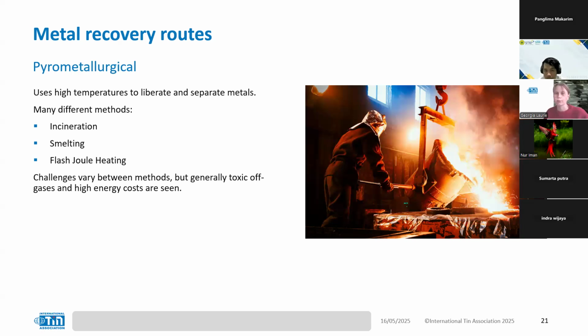This is usually a pre-treatment step to reduce e-waste volume and produce metal-rich residue. The residue can be further refined via smelting or leaching. After incineration, tin is often left behind mostly as an oxide or metal particles mixed with other ash constituents.